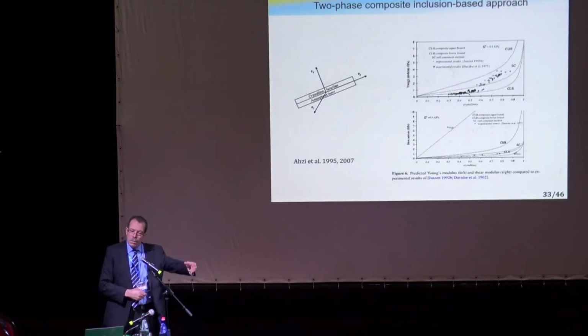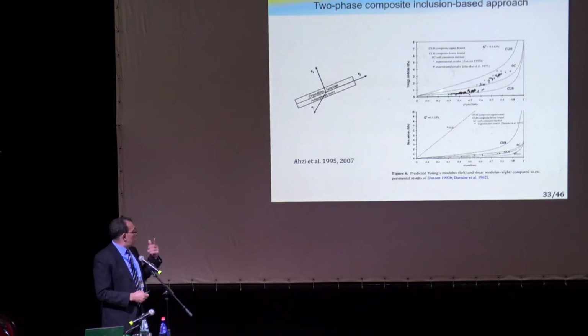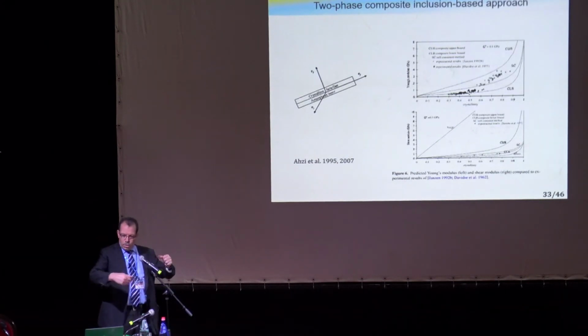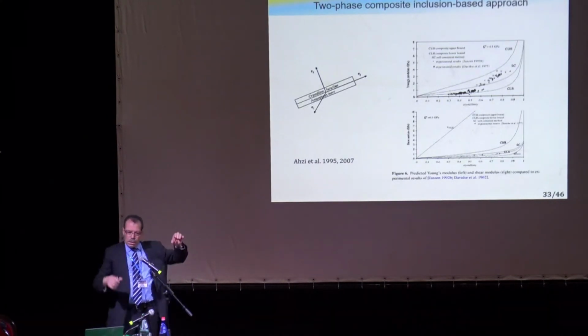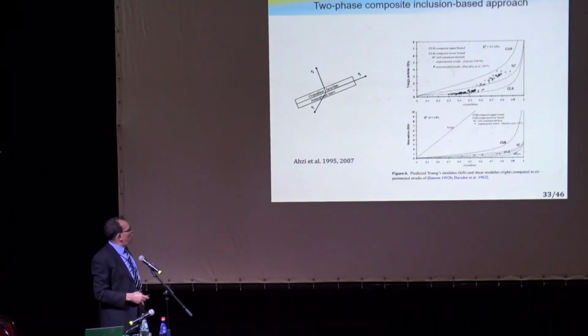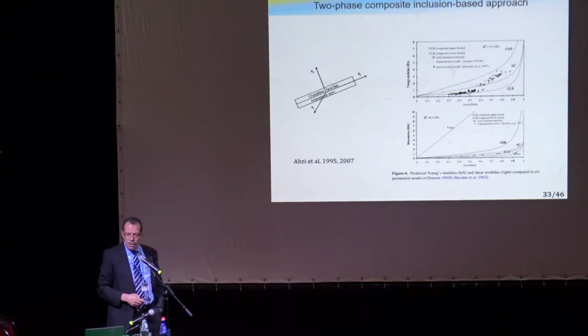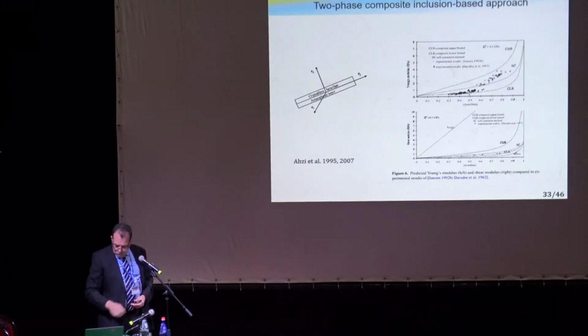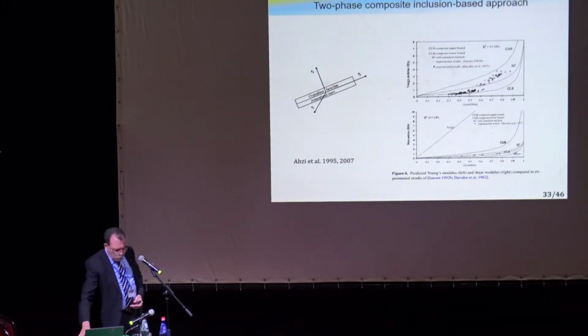And we predicted also texture and so on. In semicrystalline polymers, you have the texture of the crystal due to the crystal orientation, crystallographic. You have a texture due to molecular orientation in the amorphous, but you have another texture which is morphology, which is the orientation of these crystals. So there is also a couple of papers in 1993, I think, with David Parks and Ali Argon from MIT that we published on this in a journal, I think, Polymer.